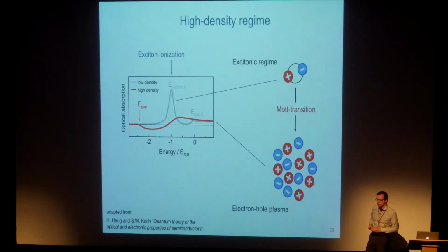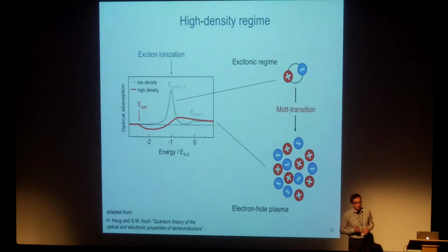Secondly, the way to think about it is that the attractive interaction is now reduced because of screening, but so does the repulsive interaction. And in a very simple picture, the repulsive interaction between carriers co-defines the absolute energy of the band gap. So if we look, let's say, at an ab initio calculation on the level of DFT of a single particle, then think about the self-energy, which comes in on the GW level, that will push the band gap up.